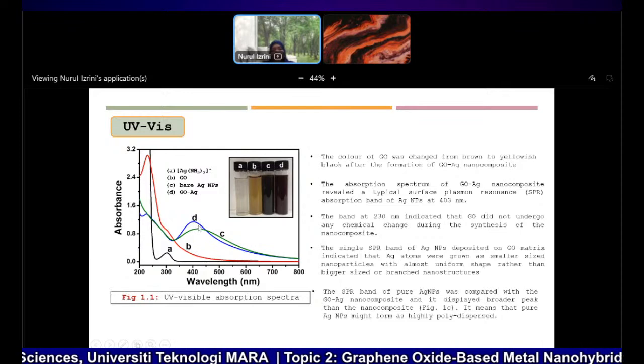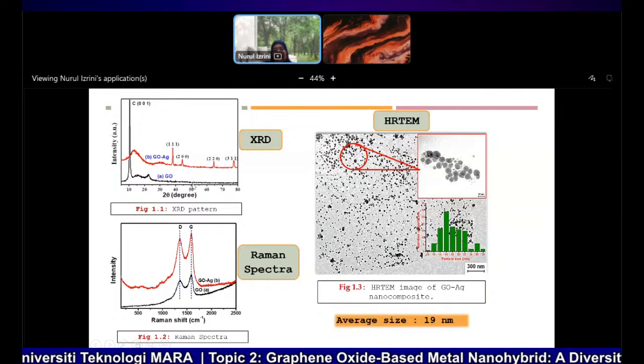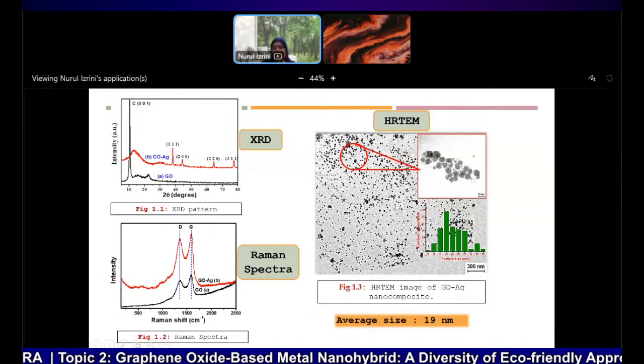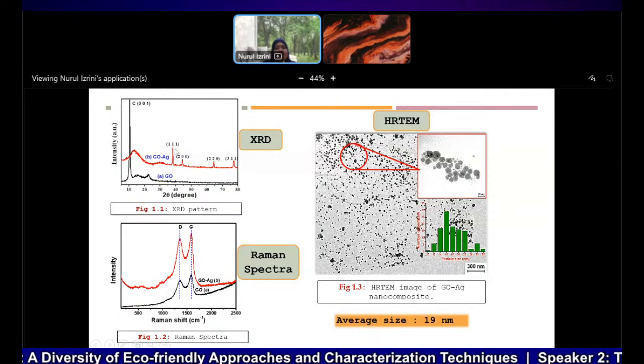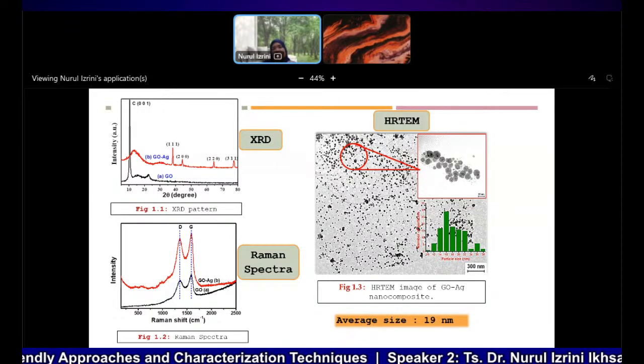And also we test, in order to study the morphology of the silver nanoparticles, we use HRTEM, and based on this HRTEM analysis, we get the average size of nanoparticle as 19 nanometers. We also confirm the crystal plane with our XRD, and we see very crystalline AG, attributed to the 111 HKL site. And then, of course, we also check the Raman spectra to confirm that our sample still has GO characteristics after the synthesis process. Based on this Raman spectra, it's confirmed that the GO is still maintained, and we can identify our formation as GOAG nanohybrids.